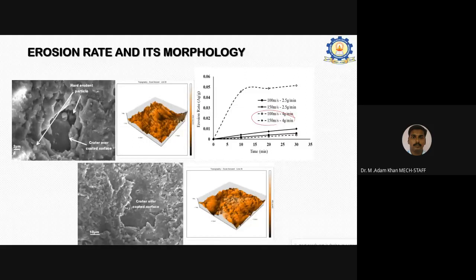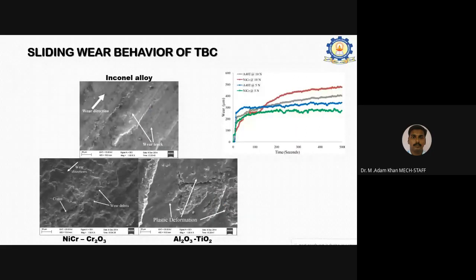Similarly, this is also my own work, published in the Journal of Surface Engineering, done for sliding wear behavior. This is pure superalloy Inconel 617. You can see the debris for nickel chromium oxide, as chromium oxide is, what to say, a metallic oxide. Wear rating compared for this and this. Alumina titania showed somewhat adhesive wear, and this one showed erosion abrasion wear, and some debris was noted in these portions.